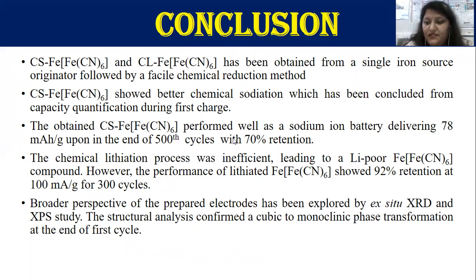So a broader perspective of the prepared electrodes has been explored by XRD and XPS study. The structural analysis confirmed a cubic to monoclinic phase transition at the end of the first cycle, which may be one of the reasons for unstable cycling during the initial stages, which provides future scope for this work in improving the stability. Such a facile, cost-effective, rapid, scalable sodiation and lithiation process has been communicated for the first time to the best of our understanding. This provides sufficient insight for preparing sodium-containing potential cathode materials.